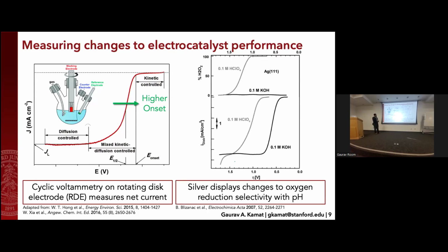So an example of an effect in terms of the microenvironment is shown here to the right, a pretty old paper from 2007, perchloric acid and potassium hydroxide on a silver electrode. So you can see, for example, the clear shift in the onset potential based on just what environment you put the same material in, but also a very large change to selectivity. In KOH, you have almost no hydrogen peroxide that's produced, but in perchloric acid, you actually do have quite a bit of hydrogen peroxide. In some cases, it's almost 100% selective.